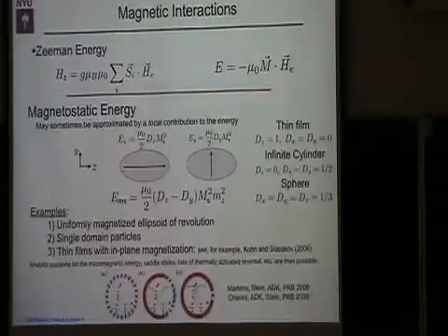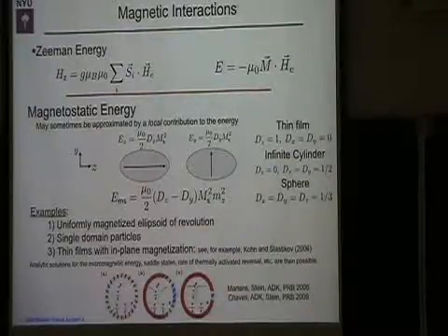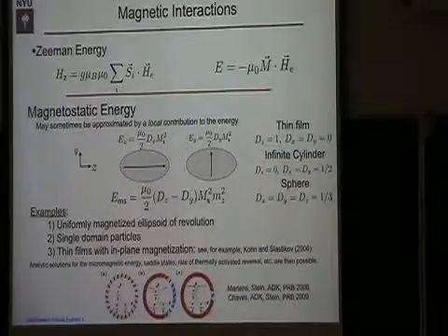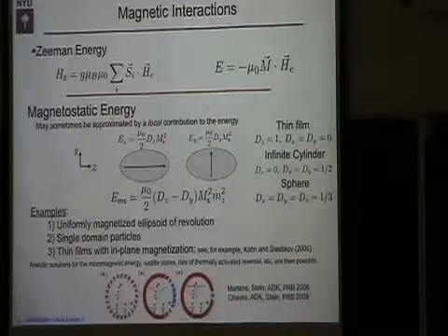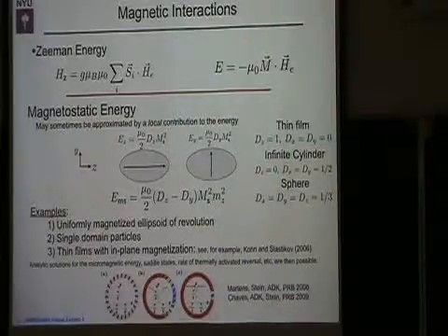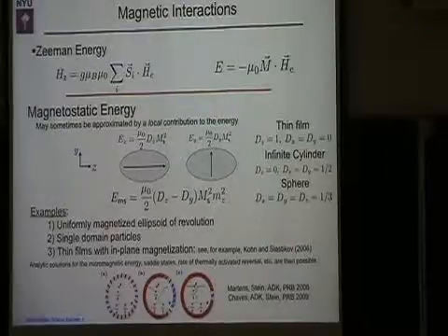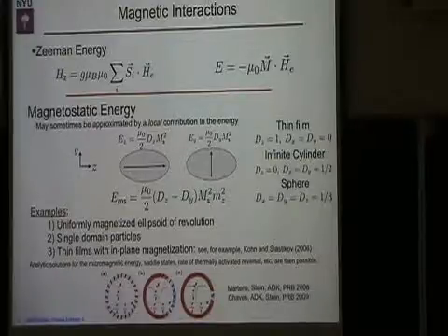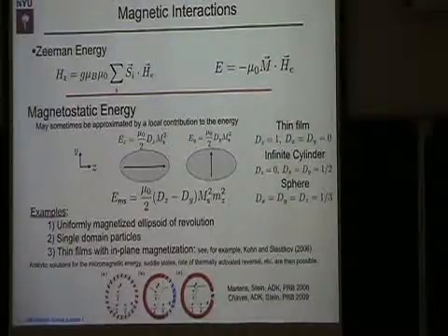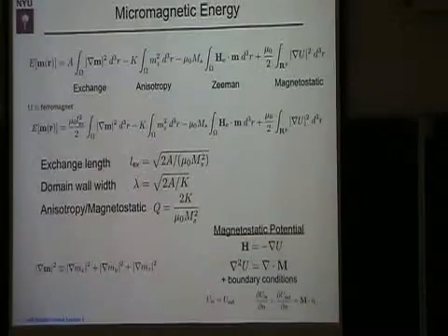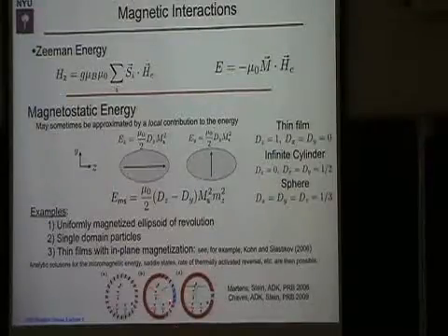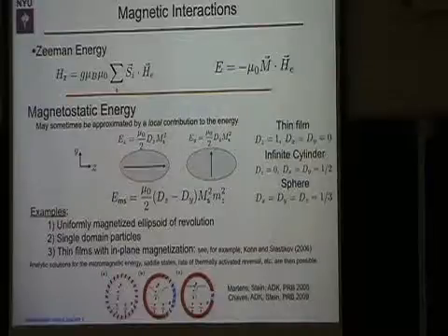There's only one metastable state, but it depends on the magnetic field and the size of the ring. But there's only one type. This state here can nucleate anywhere in the ring, so you have a degeneracy, and that actually leads to non-Arrhenius behavior. You get a prefactor which depends on that. But there is just one stable state in this problem.